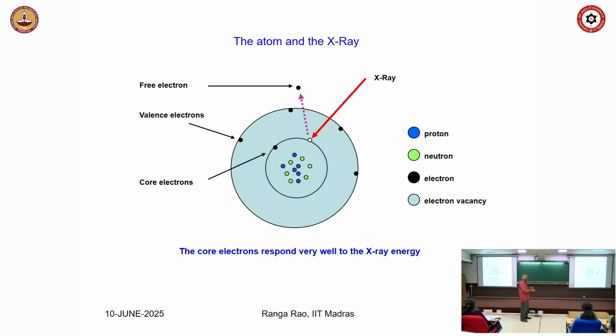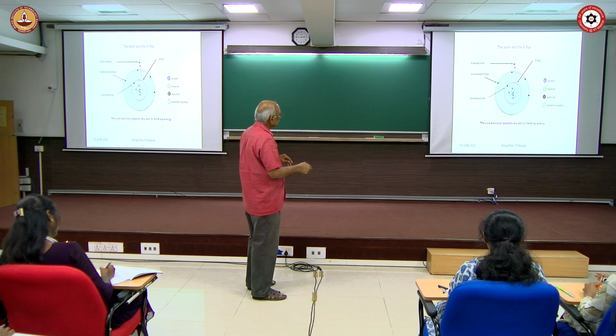So which electron will have a higher binding energy? This one or this one? Core electrons will have higher binding energy. So to remove these higher binding energy electrons from the core, you need X-rays. If you want to remove electrons from the valence levels, you need only UV light, that is sufficient. Of course, even X-rays can remove them, but UV is sufficient. So the core electrons respond very well to the X-ray energy.